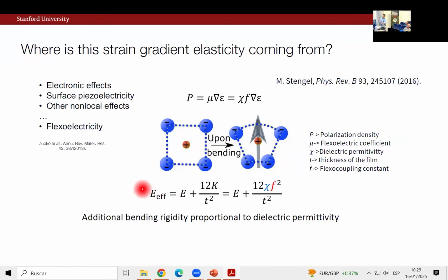So what's interesting is that if I think about this difference of having a cubic Young's modulus versus a linear response measured Young's modulus, if I express that purely in terms of some effective flexoelectric coefficient, it will go again as 1 over thickness squared, and it'll have these sorts of terms. So what does this tell us, right? Of course, these numbers matter, but if I go from the thick to the thin limit, I can go into a regime where the total elastic energy can be of order 1 contributed by this flexoelectric polarization because we're in this very thin geometry.